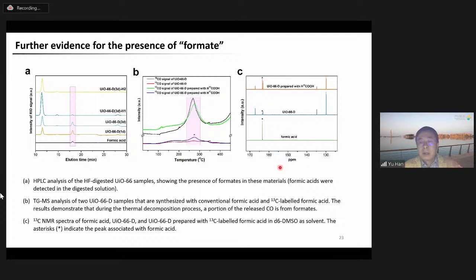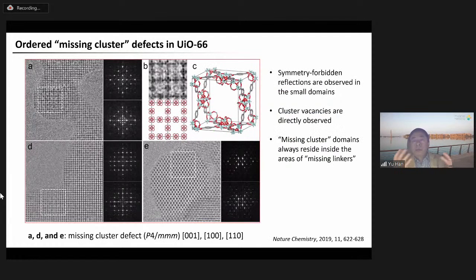And these results are consistent with our TEM reconstruction results. And interestingly, we also observe ordered missing cluster defects in the same sample. Ordered missing cluster defects in UiO-66 have been speculated before based on diffraction data, because in the diffraction data, people can see the symmetry forbidden reflections show up. But with TEM, we can see these defects and their distribution directly in real space.